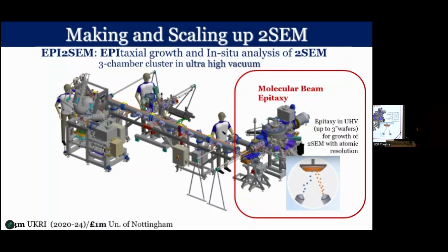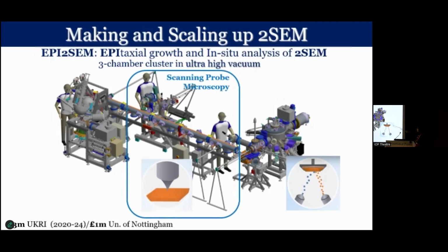This is how it works. Element is sublimated from the solid source and then crystallized on a substrate that is kept at a given temperature. So this is done by a technique called molecular beam epitaxy. Then in ultra high vacuum, we take the sample to the second chamber where we look at the morphology using techniques like scanning tunneling microscopy or atomic force microscopy.